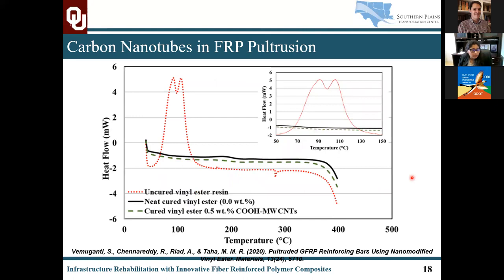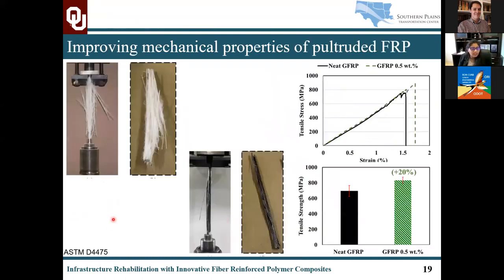It has also been very effective to understand that the carbon nanotube modifications in the vinyl ester resin have not affected the curing process of these resins. Both the cured vinyl ester neat without any nanomodification and the cured vinyl ester with a slight amount of nanomodification with the carbon nanotubes have shown 95% of curing capabilities. Under tensile loads, there is a very good improvement of 20%. The main idea is to see brittle explosive failure in a neat FRP, whereas there is not such brittle and explosive failure in a carbon nanotube modified FRP.